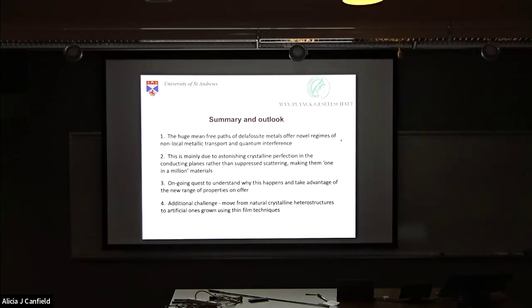I'm also still concerned about this item 1 and 2, and a couple of things. First, you mentioned that the impurities in the whatever bed layer are well screened, but it should be the other way around. You have very high Fermi velocity, which means low density of states, and low density of states is actually low screening, bad screening, not good screening. You expect good screening to be in very heavy materials with large density of states.